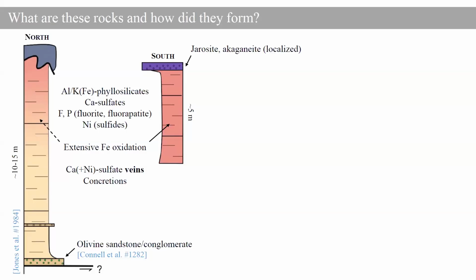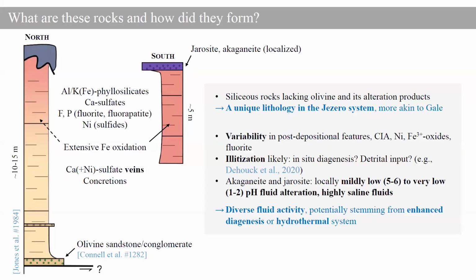Now, if we go to the next slide and start thinking about implications, the first thing to note is that, apart from a very thin level of olivine-enriched rocks, which Steph Connell will talk about at the end of this session, most of the rocks are relatively rich in silica and they are broadly lacking olivine. So this is a quite unique lithology in the Jezero system, and which seems more akin to Gale crater, for example. A second observation is that its composition is relatively stable within the stratigraphy, and the variability we see is related to leaching of mobile elements, to iron oxides, to the presence of fluorite, veins, concretions, and so on.